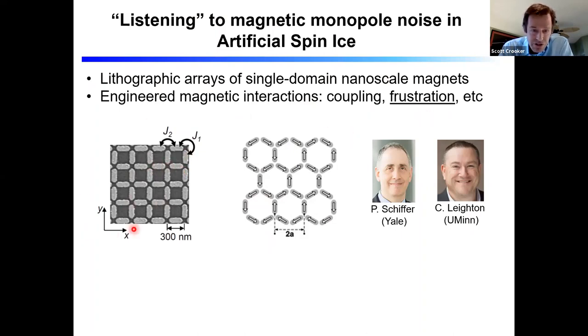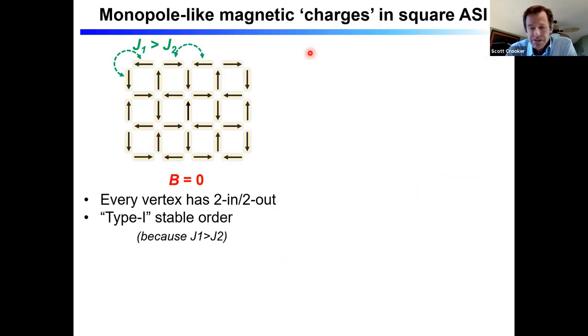This is a SEM of just a square spin ice lattice. This is a picture of a kagome or a hexagonal ice lattice. Now, anytime we talk about spin ices, the subject of magnetic monopole or magnetic monopole-like quasi-particles always comes up. So let's talk just a little bit about how this happens. Starting with just the most boring canonical artificial spin ice, which is a square lattice. As shown here, we've got islands on a square layout. There's a coupling between adjacent horizontal and vertical islands. This is what we just call J1. And there's a weaker coupling between adjacent horizontal or adjacent vertical, side by side elements. We call this J2.